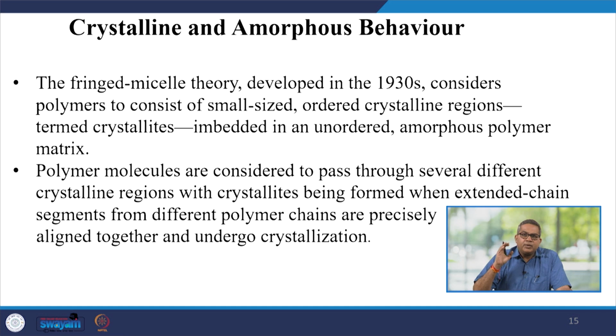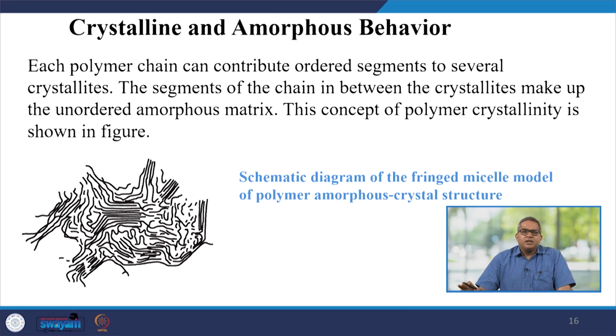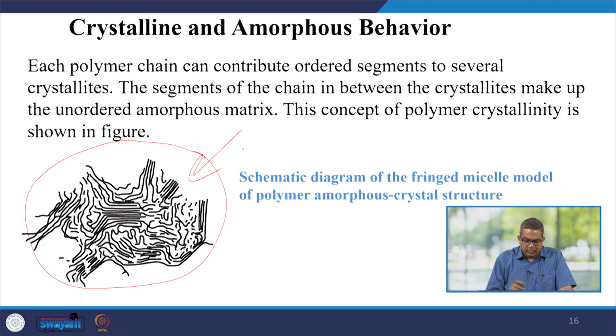The fringed micelle theory, which was developed way back in 1930, considers the polymer to consist of small-sized ordered crystalline regions. They are termed crystallites. They are embedded in an unordered amorphous polymer matrix. So, the polymer molecules are considered to pass through several different crystalline regions, with the crystallites being formed when extended chain segments from different polymer chains are precisely aligned together and undergo crystallization. Now, each polymer chain can contribute ordered segments to several crystallites. The segments of the chain between the crystallites make up the unordered amorphous matrix. This particular aspect is presented over here. This is a schematic diagram of the fringed micelle model of polymer amorphous crystalline structure.